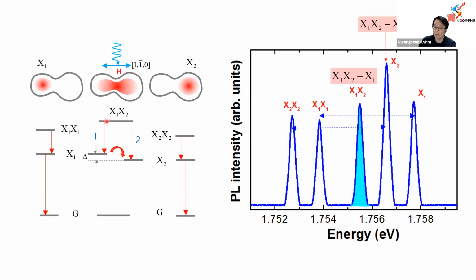But when you consider the transition of the coupled biexciton to the different excitons, X1 and X2, there should be 2 transitions, but I marked only 1. So actually, 2 transitions are associated here, X2. We found, by chance, the transition 2 is overlapped with X2. Simply these 2 energy levels are exactly the same, so it's overlapped. That's why the magnitude of X2 is a bit higher compared to X1. And in fact, this one corresponds to the transition 1.